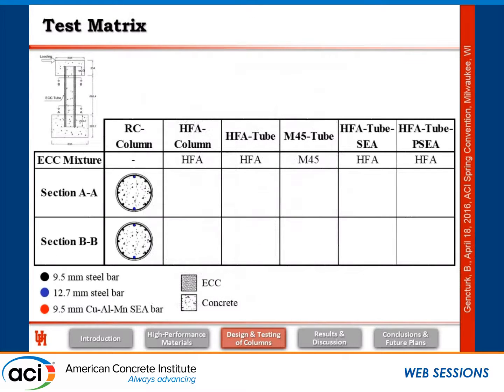Now, we tested 6 columns. So the first column, these are the cross-sections here at the plastic hinge region. AA is the cross-section in the plastic hinge region. BB is the cross-section above the plastic hinge region. This is the conventional concrete column. So the black circles here are the number 3 bars, if you like, and the blue ones are the number 4 bars. On the neutral axis, these are tested in uniaxial bending. So these blue bars, or if you want to cut it vertically, that's where the neutral axis is.